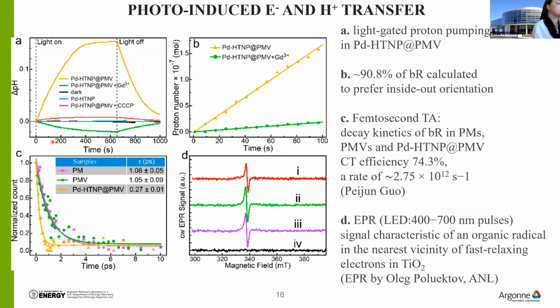And here you can see this is a difference in pHs. It's an increase of pH in the bulk solvent outside of the nanoparticles. So upon light illumination, you can see pH is going up, and then light is off. It's due to backward reaction, backward transfer is going off.